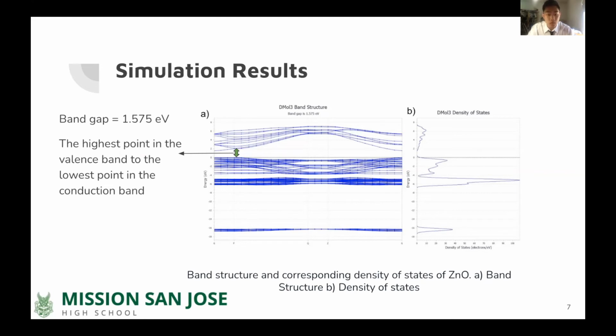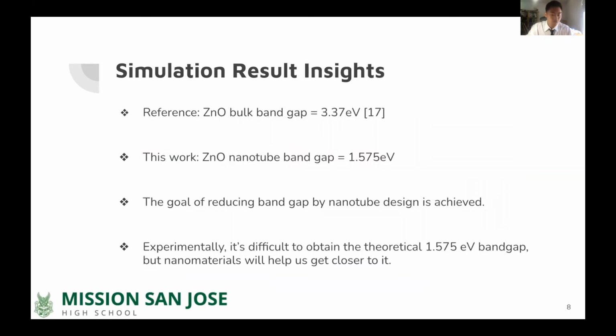With the evidence of our computation and other researchers' work, band gap can be decreased by decreasing the size of crystallites. The band gap represents the minimum amount of energy required for electrons to become excited, thus increasing conductivity. Therefore, we want the band gap to be as small as possible. The band gap of zinc oxide nanotubes is less than 2 electron volts, making it a viable choice. Experimentally, it's difficult to obtain the theoretical 1.575 electron volt band gap, but nanomaterials will help us get closer to it.